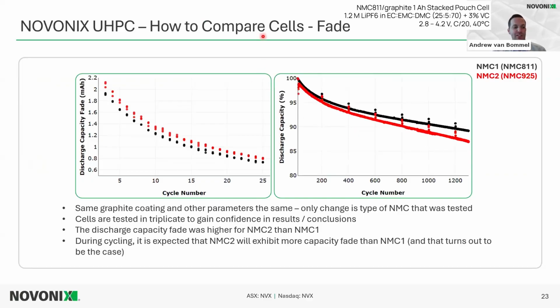So here's how to compare cells, as I mentioned, by looking at fade. We see discharge capacity fade is measured by UHPC, and there's 25 cycles. And this red cell, these are both NMC, but the red is NMC 925. So if you asked yourself, should I switch my cell to this NMC 925 as compared to the 811, which is about 80% nickel? You could do UHPC. You see in this case, this NMC 925 has higher discharge capacity fade than the NMC 811. And you would have confidence pretty early, even within 5-10 cycles. So this might be within only a week. You could know, okay, maybe we shouldn't go with that 925.